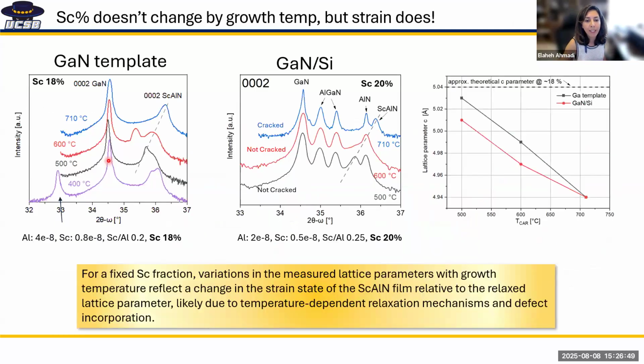Now in our new efforts here, we've been working on scandium nitride growth on both GaN templates, and by that I mean GaN on sapphire and GaN on silicon at the same time, to see if the growth is different, because there is also growing interest in GaN on silicon, for other purposes like where silicon can be removed easily, the substrate, for other applications. So we have looked at growth temperature, fluxes, scandium to aluminum ratio. And one thing that is interesting with temperature is that even though the scandium content doesn't change by temperature as we go from 400 C to 710, as we change the growth temperature, the strain state of scandium nitride films is changing, and that's probably due to temperature dependent relaxation mechanisms and defect